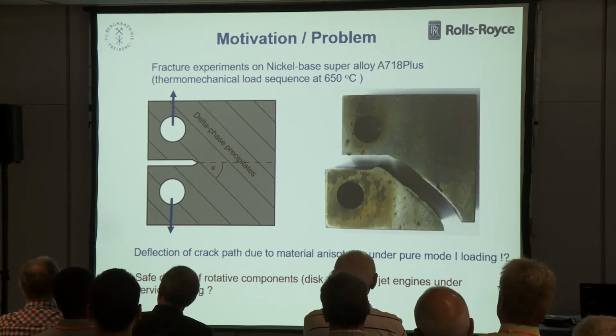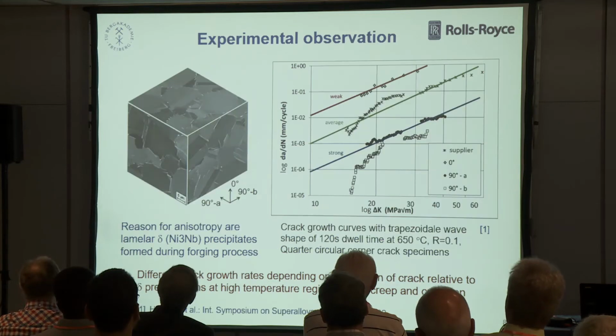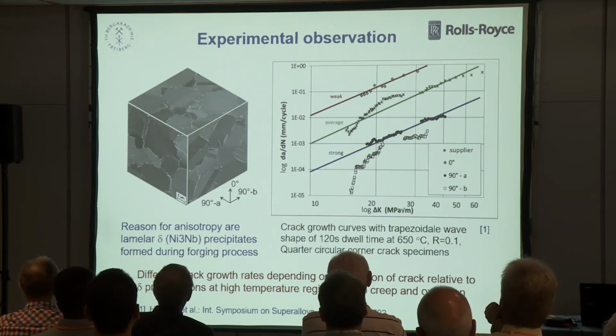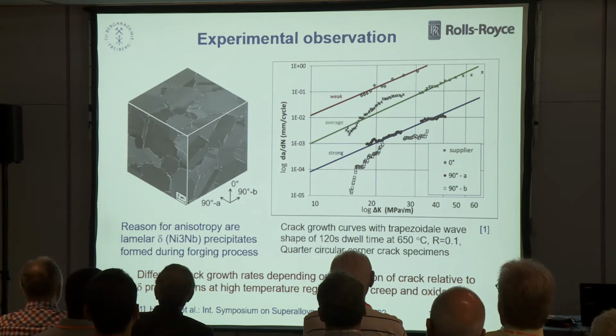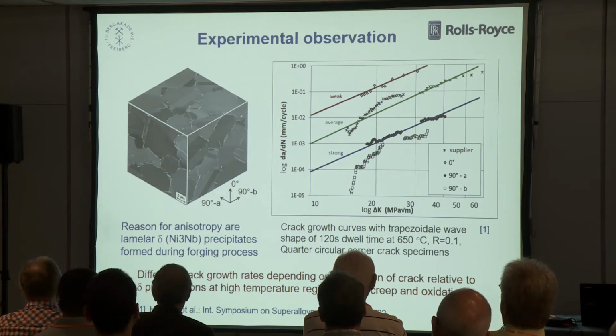phase precipitates, here with an angle alpha. Here you see the microstructure. The white lines are these precipitates. These are delta nickel niobium precipitates. These are formed during the forging process of the material along the forging lines.